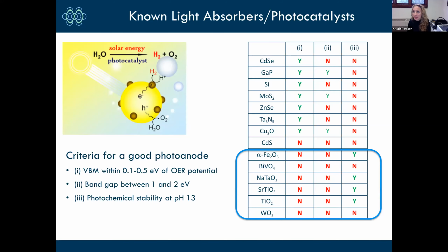So in those days, this project is now a few years old, we looked at the existing body of known photocatalysts for oxygen evolution. And there were the semiconducting families that you see did pretty well on criterion number 1. So you see a lot of green yeses there. Sort of okay on criterion number 2, but really quite badly on criterion number 3. So yes, good electronic structure properties, but not so stable in the environment where you need the material to operate. It doesn't really matter how great of a band gap and how well your bands are aligned if your material is either going to decompose, form a passivating film on the surface, or dissolve in the environment that you're designing it for.